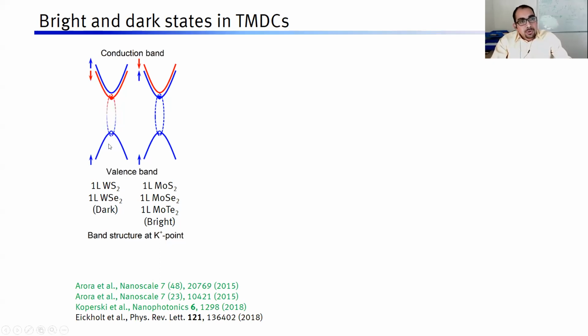The point is that if you want to make any transition in these two-dimensional materials, then the spins have to be preserved. But here the lowest state, which will be most occupied at low temperatures, would have an opposite spin compared to the top of the valence band. So therefore, this transition is not possible. Unfortunately, if the material has such a band structure, it is not an efficient emitter of light, because most of the carriers will be frozen at low temperature in this state in the conduction band, and then you will not have recombination possible. So that's why these materials are called dark materials, because they won't be an efficient emitter of light. However, in molybdenum-based materials, the spins are inverted in the split conduction band. So this splitting is due to spin orbit coupling. And then this transition is possible, and they should be bright materials.